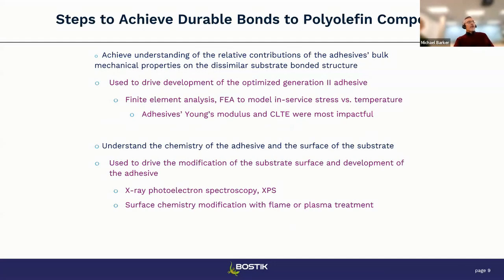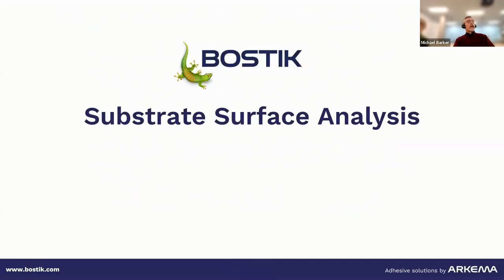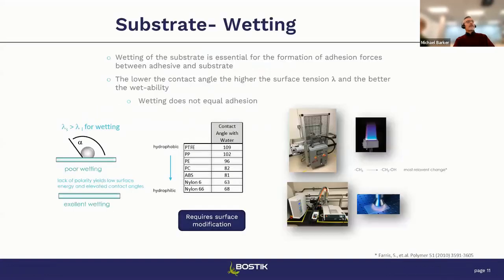So our approach, we took 3 different approaches. One, we wanted to understand how the constitutive properties of the adhesive would impact the adhesion and the durability. 2, we used finite element analysis to model the in-service stress. And of course, then within that model, we could change the properties of the adhesive. And the outcome of that was that the Young's modulus of the adhesive and the CLTE of the adhesive were most impactful. And then the third area was to understand the chemistry of the surface of the substrate and how the adhesive would interact with that. In that regards, we used X-ray photoelectron spectroscopy to not only understand the surface chemistry, but how that could, as I pointed out, interact with an isocyanate-based polyurethane.